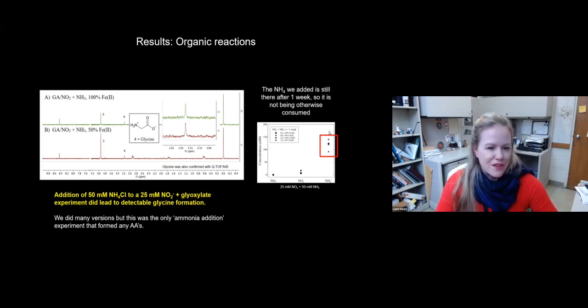And we did not observe any glycine formation from glyoxylate until we got to 50 millimolar ammonia. That's strange because, as I showed previously, even at low ammonia concentrations, like 5 millimolar, we did see glycine formation from this precursor. We also see that the ammonia we added is still there. We detected it after 1 week, so it's not being otherwise consumed. It's not escaping from the system somehow.